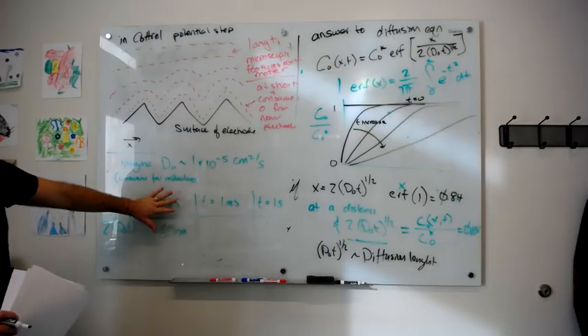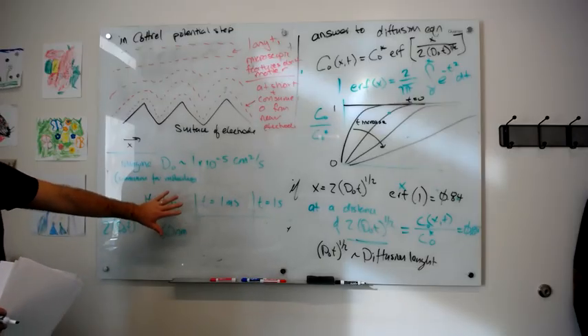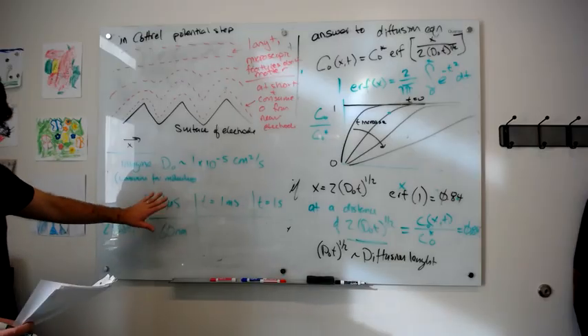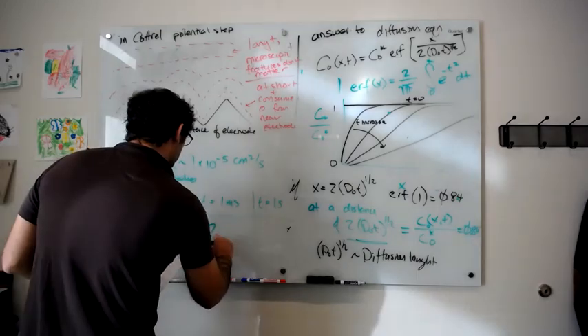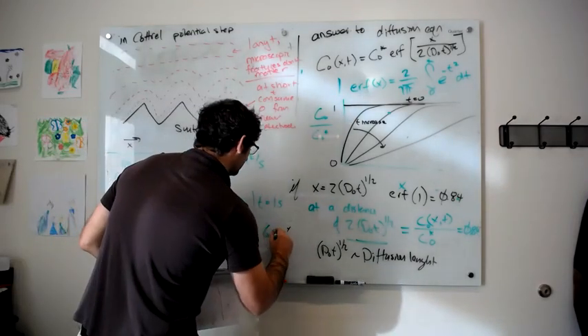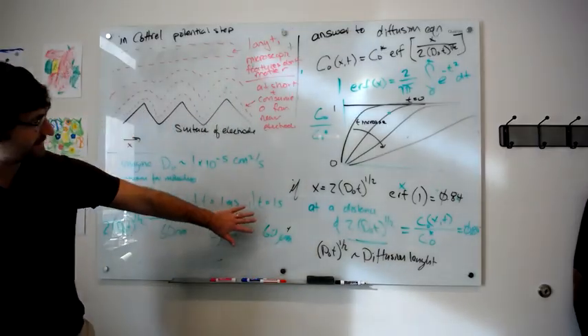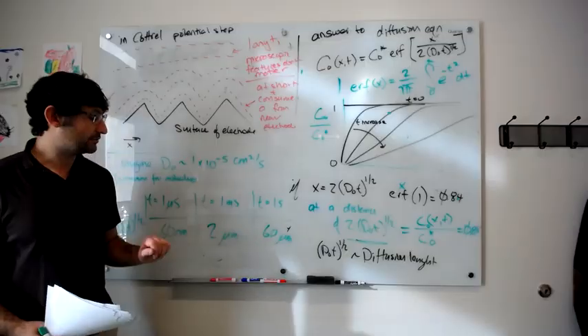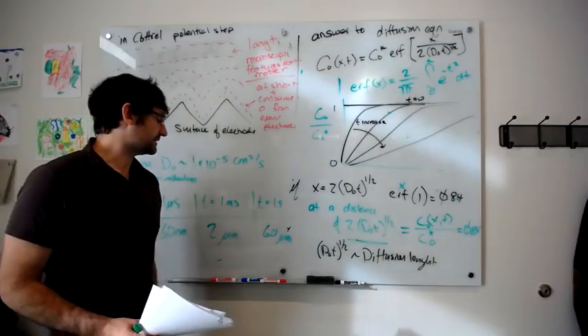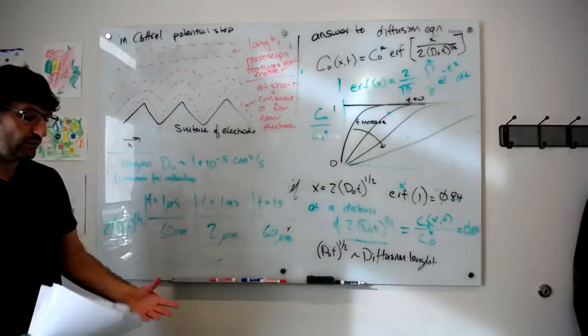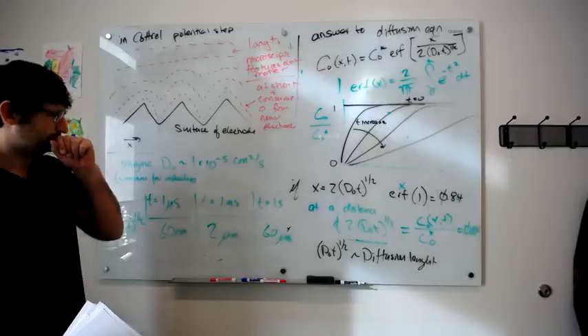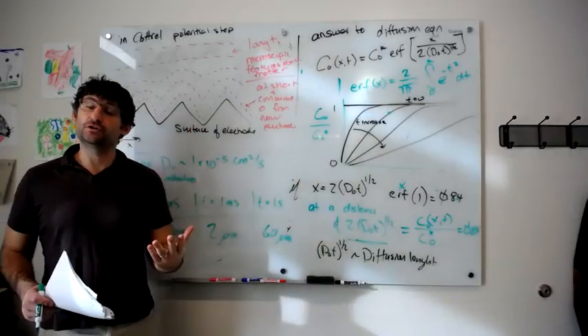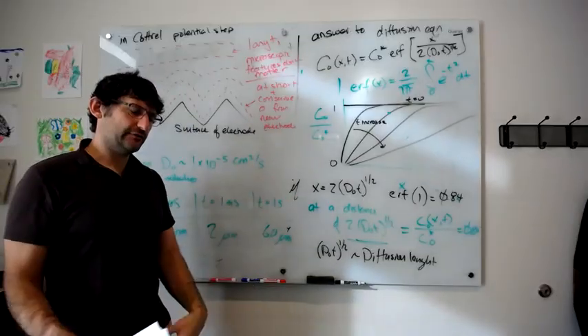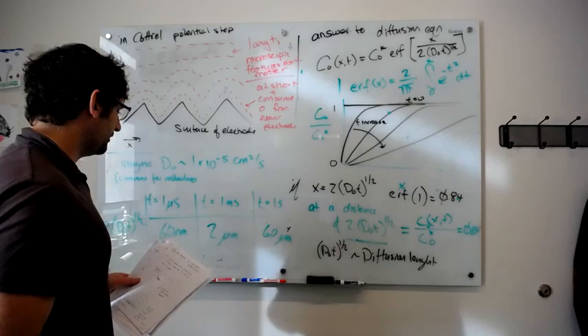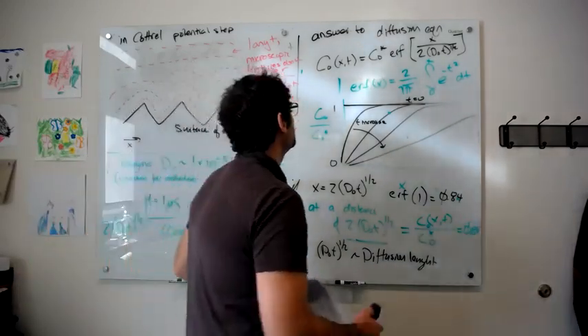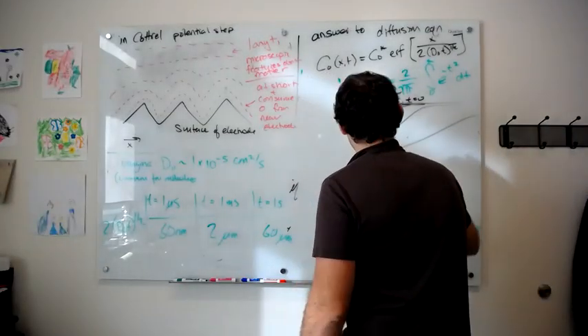So all your roughness that you can't see by eye is going to be smaller than this. So that all happens on a time scale of about 1 microsecond, which is quite fast in electrochemistry. 2 microns in a millisecond, 63 microns in a second. So by a second, you're actually already pretty far, pulling stuff pretty far from the electrode surface. This is fractions of a millimeter, right? So 100 microns is a tenth of a millimeter. So in a few seconds, in 10 seconds, 20 seconds, you've pulled stuff out at almost a millimeter of the electrolyte. And of course, this whole approach breaks down when you get to those longer time scales, because you start having these convective currents that make the boundary conditions no longer true. Okay, so let's think about this now when we shrink the dimension of the electrode down very small. And you'll see why this is important in a second.